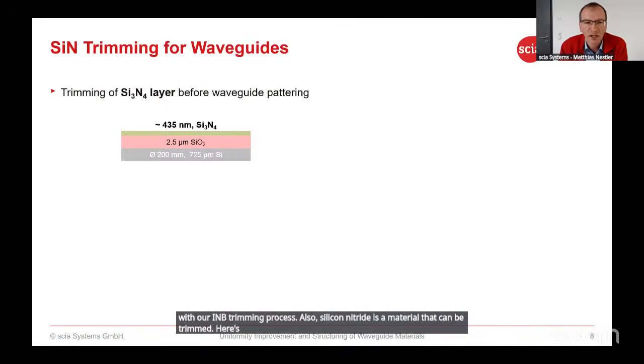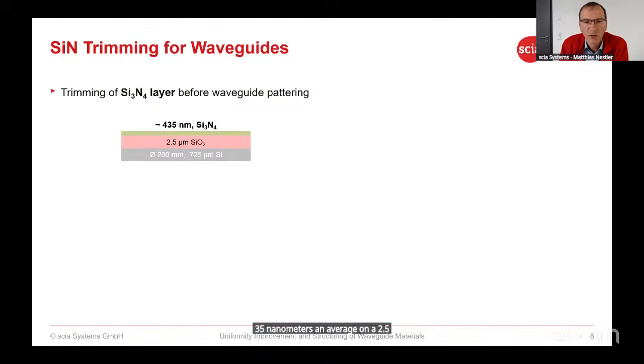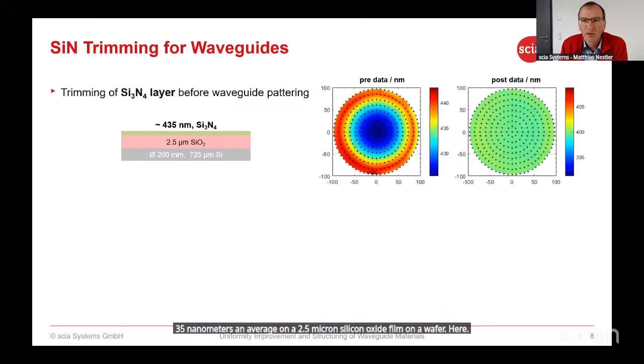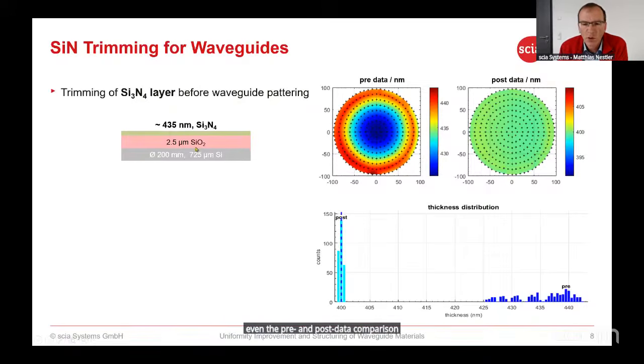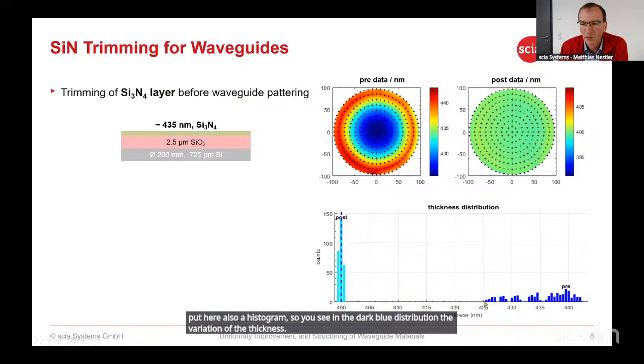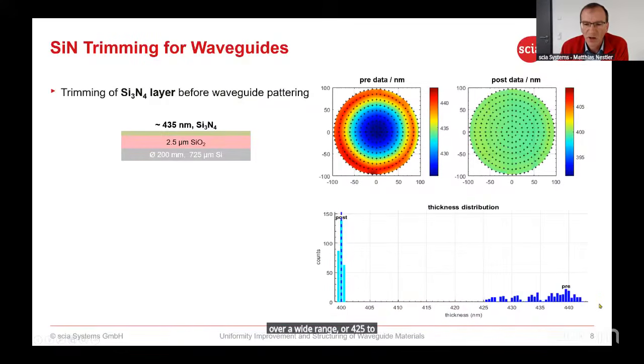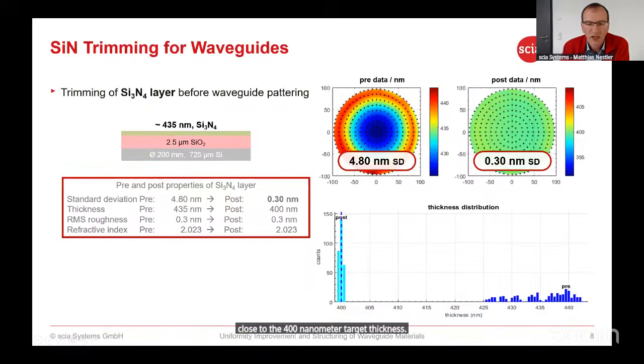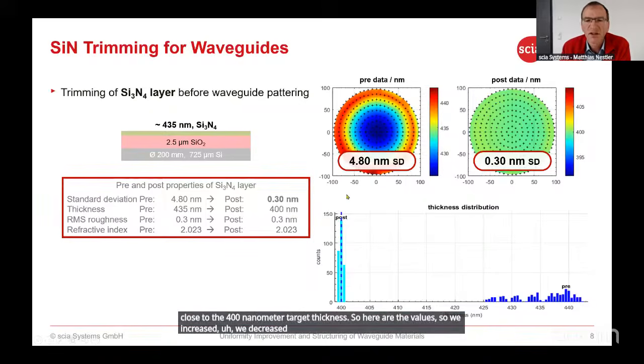Here's an example of a silicon nitride film of 435 nanometers on average on a 2.5 micron silicon oxide film on a wafer. Here, even the pre and post data comparison. To make it more visible, I have put here also a histogram. So you see in the dark blue distribution, the variation of the thickness over a wide range of 425 to 450 nanometers, while after our ion beam trimming, all the measurement spots are close to the 400 nanometer target thickness. So here are the values. So we decreased the standard deviation from 4.8 nanometer down to 0.3 nanometer, really atomistic level, what we achieved.